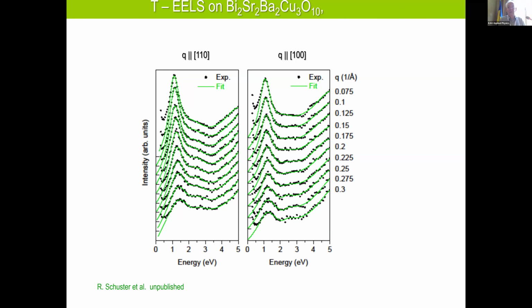But there are two explanations. One is that in the tri-layer system, you have different doping. The outer layers are strongly overdoped, and the inner layer is underdoped. So maybe in the underdoped layer, correlation effects are important. The other explanation would be that within the tri-layer system, you may have anti-phase oscillation, which could also change the dispersion at higher momentum.